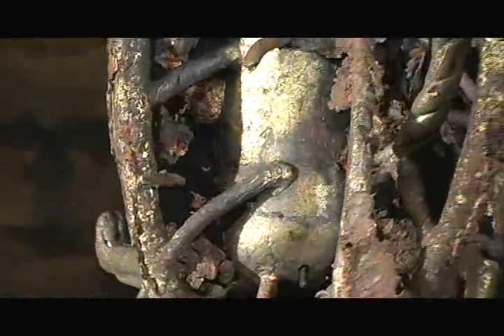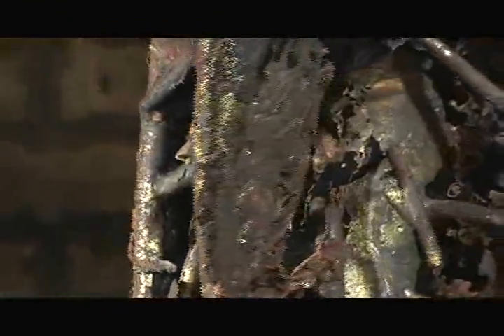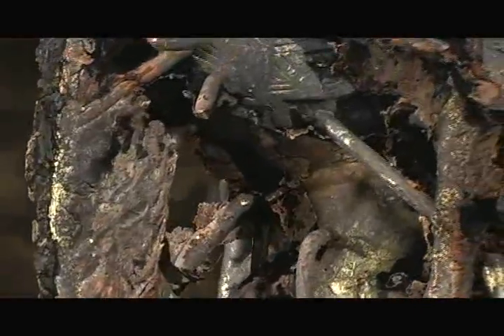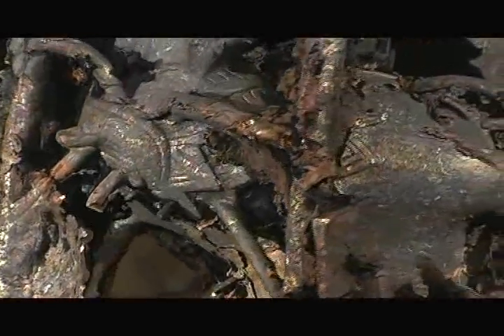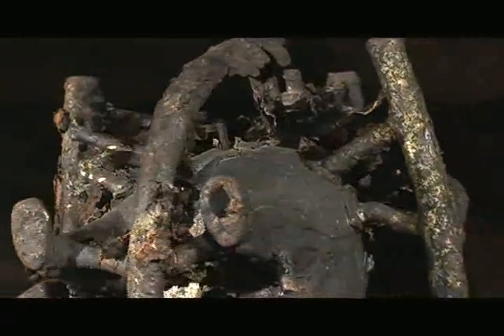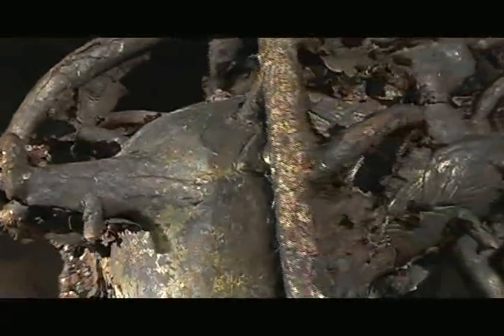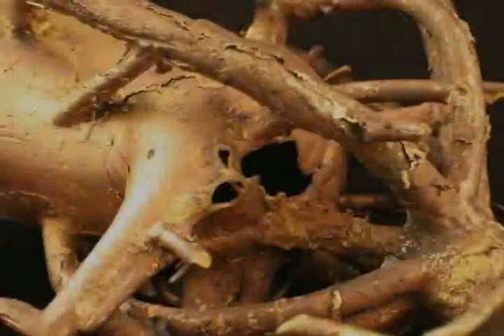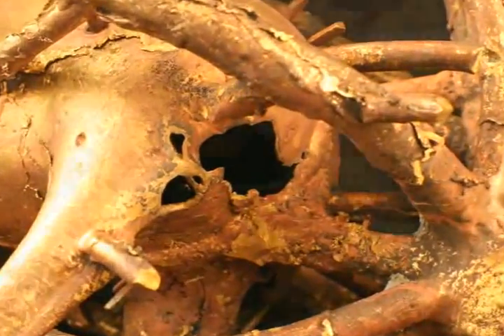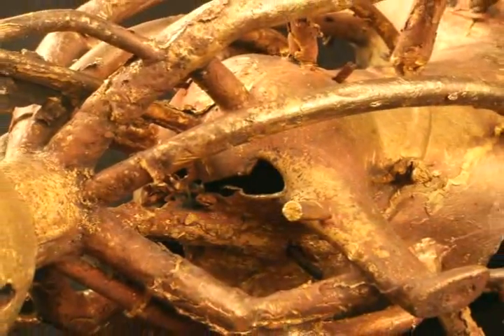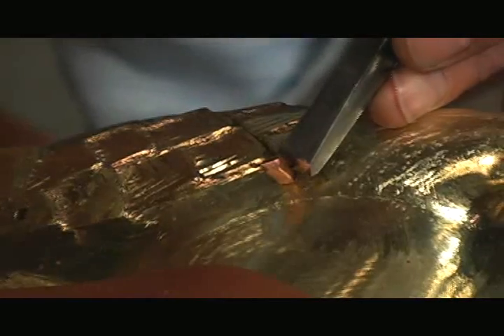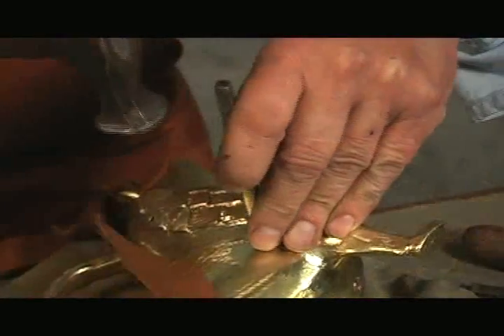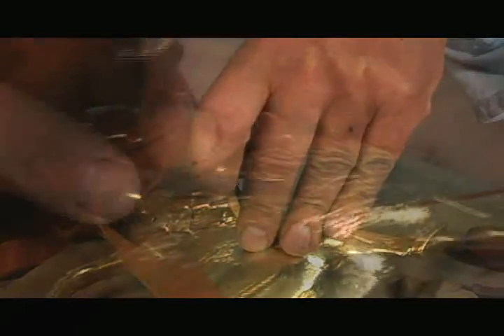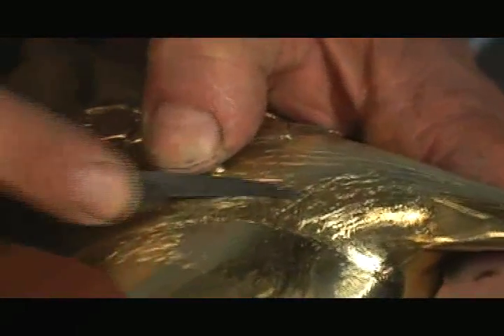Larger casting flaws were generally repaired at this time with cast-in fills, similar to those on the original lion's buttocks. Interestingly, even with our extensive gating system and our pre-knowledge of the existing flaws, our casting replicated the flaws of the original. Smaller voids might be filled with blanks, shaped to size, and hammered in. The core pins were generally knocked out and filled with copper plugs, hammered in without the addition of solder. Their presence was disguised by working the surrounding metal over their exposed surfaces.